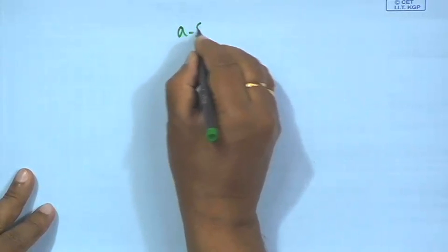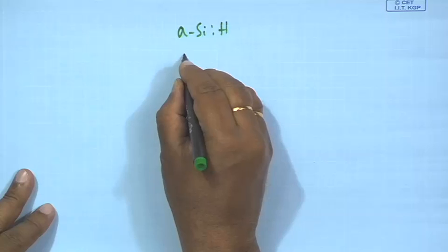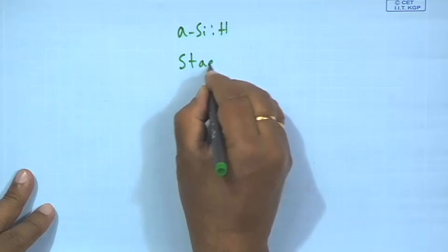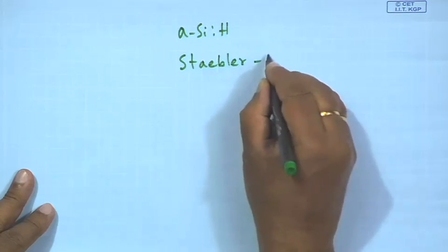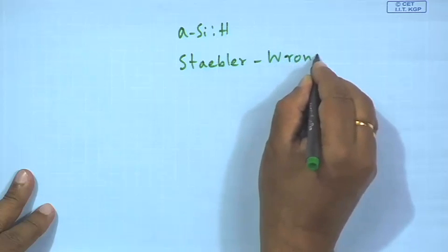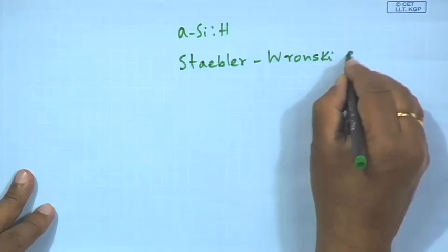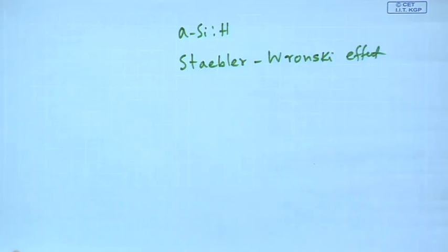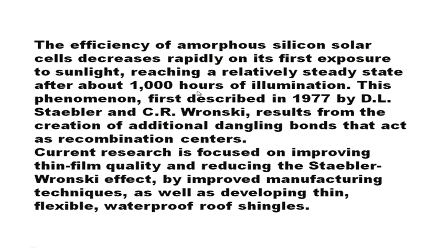In the case of amorphous silicon solar cell, the problem is the Staebler-Wronski effect, S-T-A-E-B-L-E-R, Staebler-Wronski, W-R-O-N-S-K-I. This Staebler-Wronski effect is the effect that within the first 1000 hours of illumination, the recombination centers increase, additional dangling bonds increase. So, there is a stable efficiency after 1000 hours of illumination. Say if it is 12%, then after 1000 hours the stable efficiency can be say 8%, 9%.